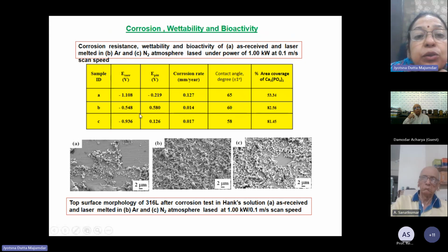So if you see the corrosion, wear and wettability results, you will find that in argon and in nitrogen environment, if you see the Ecorr value, it also shifts towards the noble direction as compared to that of as-received AISI 316L stainless steel. So pitting corrosion, normal corrosion tendency, or reactivity decreases, the overall reactivity of the surfaces decreases, and the Epit value also shifts significantly towards the noble direction. So you can say pitting corrosion resistance is also improved significantly for both argon and nitrogen environment.